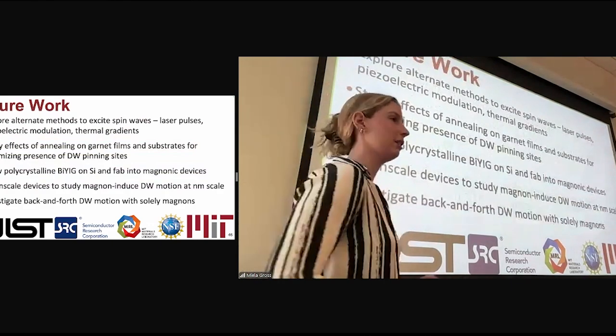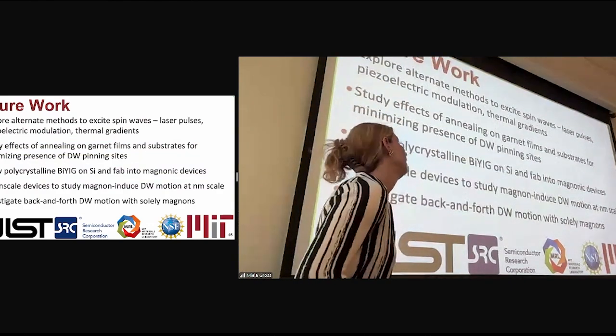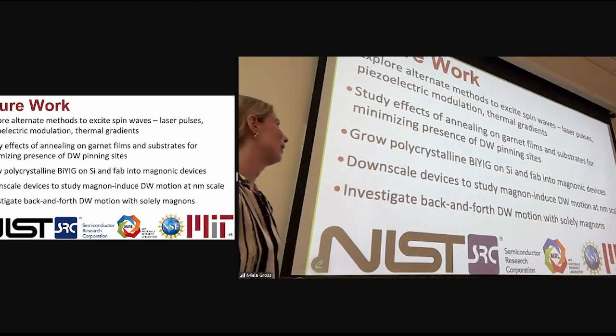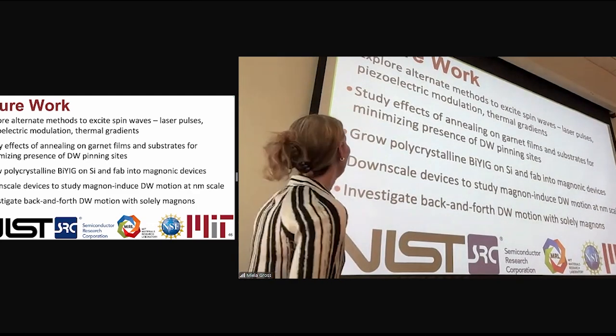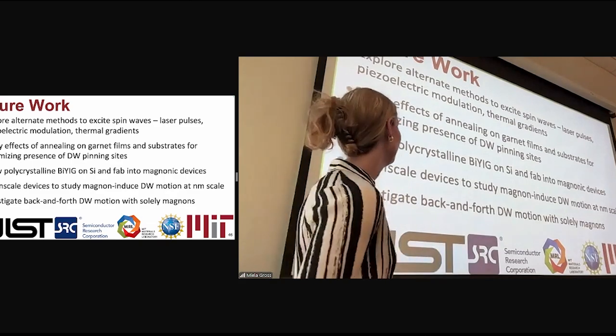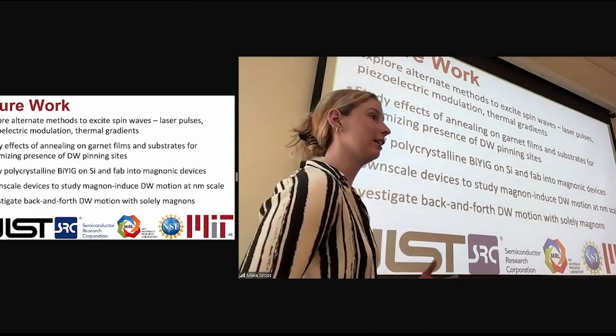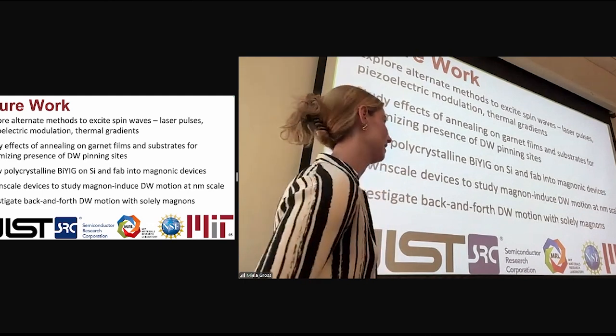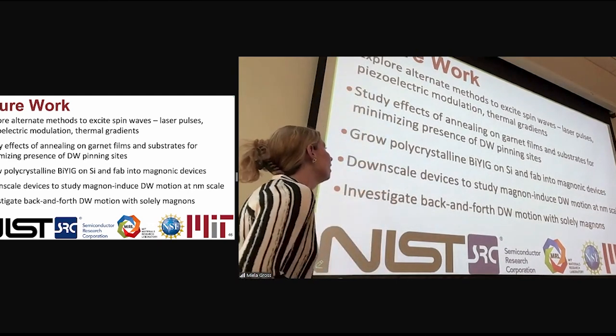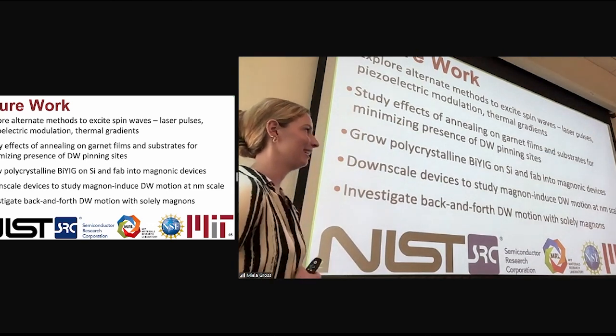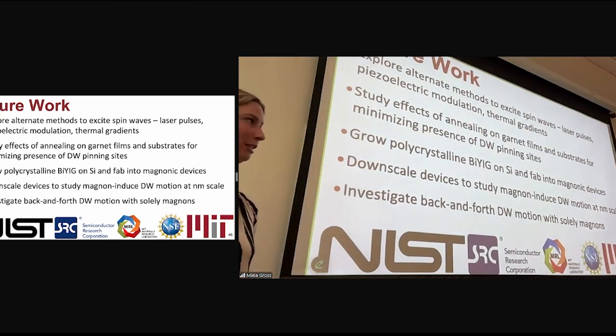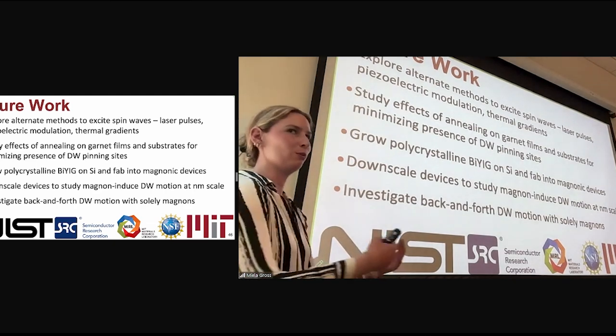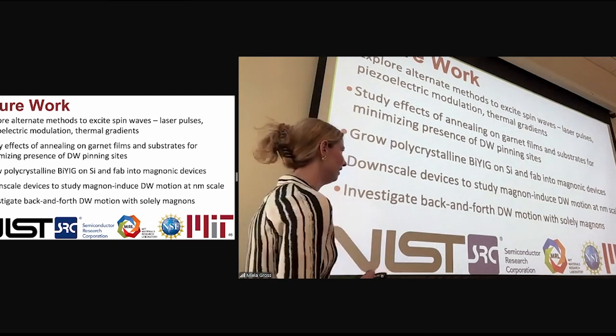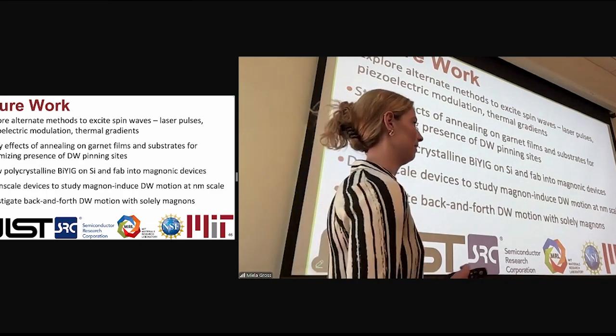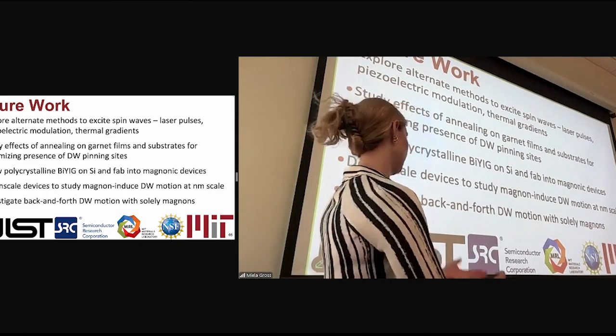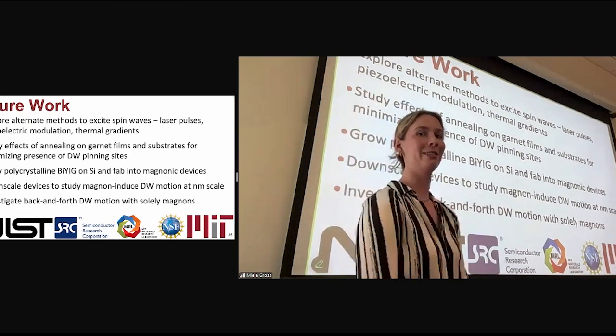And there are a lot of different directions you could take this work moving forward. If I was here at MIT for a couple more years, I would probably want to expand on the spin wave domain wall work and explore alternate methods to excite spin waves, and also study the effect of annealing on garnet films and substrates. We've shown that really has a strong effect on domain wall pinning sites. Also, growing polycrystalline bismuth-YIG on silicon and then fabbing that into devices would be really interesting to try. It would bring the work one step closer to CMOS integration. And then also just downscaling these devices to study this effect on the nanometer scale, and maybe even try to get this back and forth motion with just magnons and no external fields.